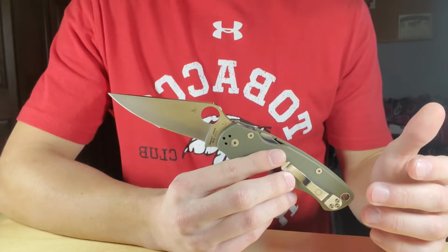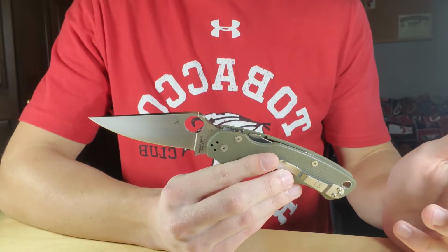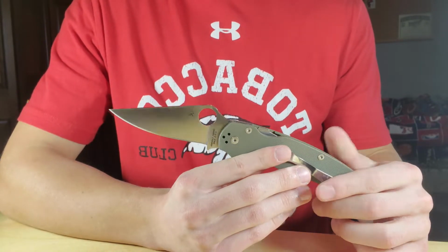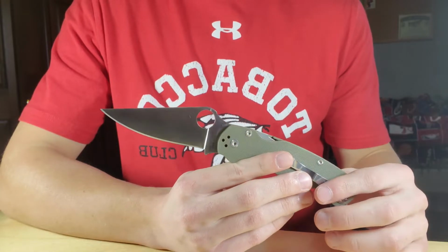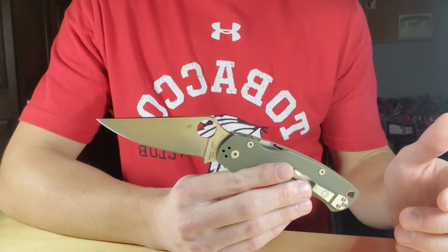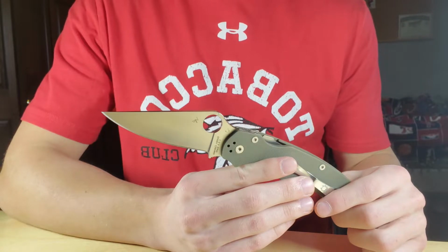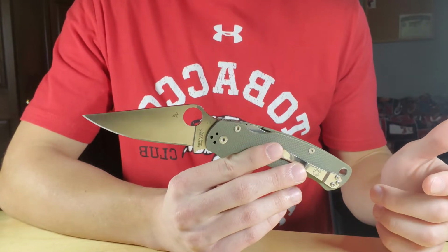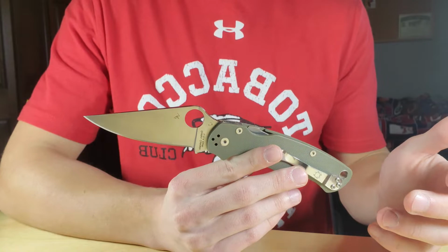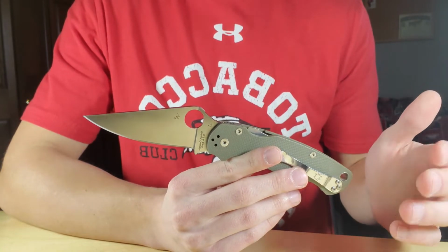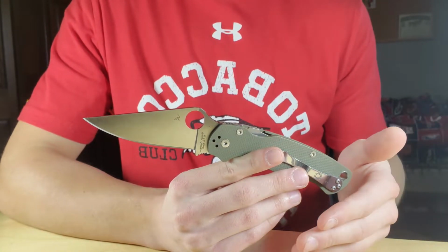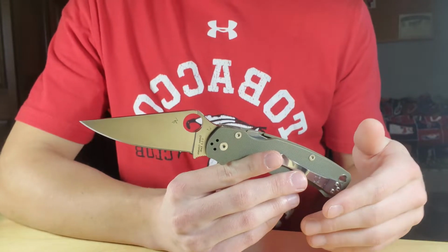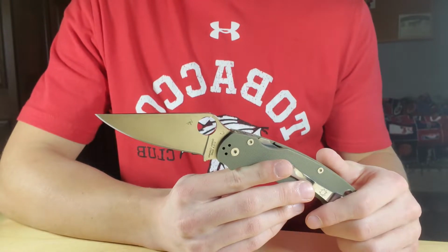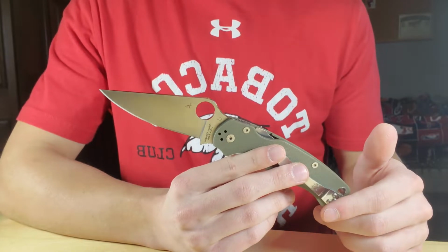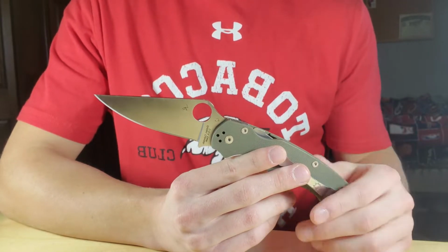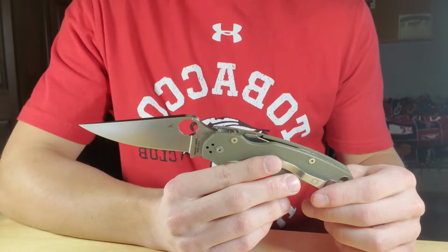The steel hardness itself isn't really the issue. It's the carbide hardness. Carbides can be much harder than the steel matrix that they're surrounded by. So like this K390 PM2 is coming in between 63 to 64. Most stones are going to be able to abrade that. That's not crazy hard for most stones. But when you start thinking about the carbides that are inside of it, vanadium, vanadium's the main one, I believe, in K390, that is much, much, much harder than the steel matrix around it, and most stones aren't going to be able to touch that.